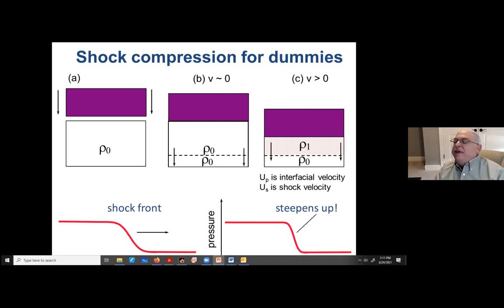I will say that the fastest shock wave I've ever seen was in sapphire, which is very stiff, and it was 1 picosecond. So the shock wave can be pretty fast, but if you have an inhomogeneous material, we'll have some shock wave scattering, and it won't necessarily be so fast.